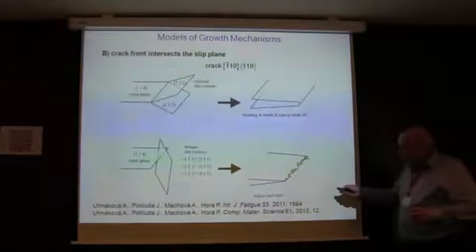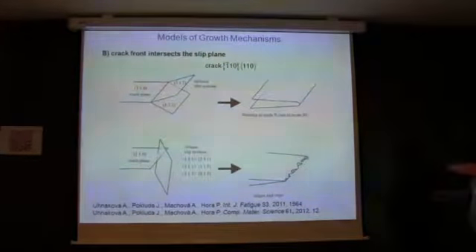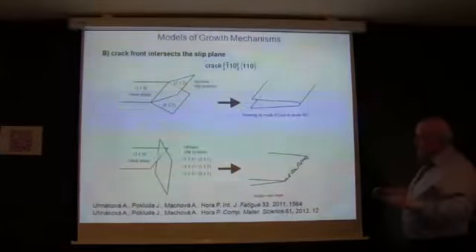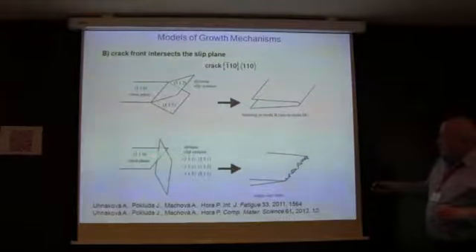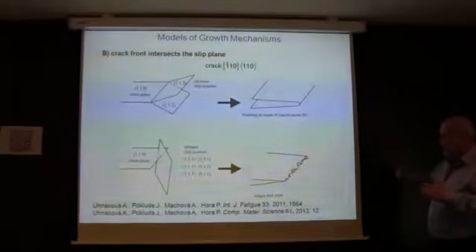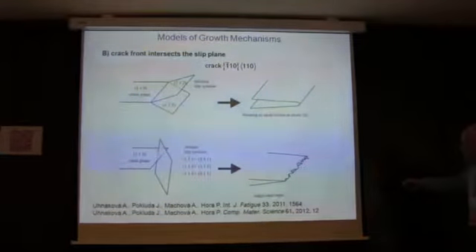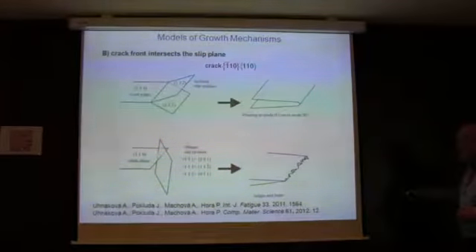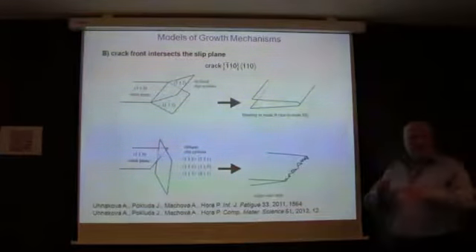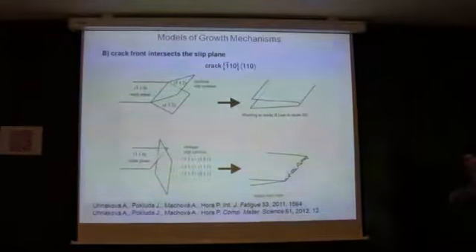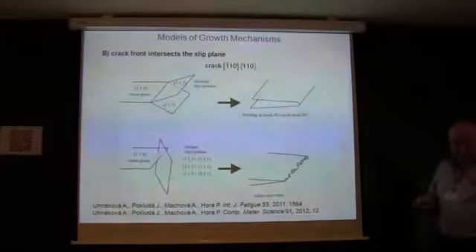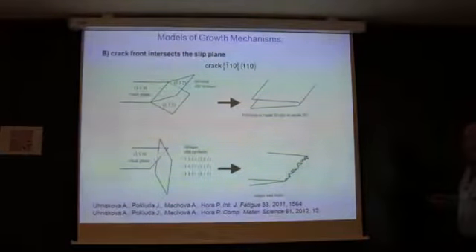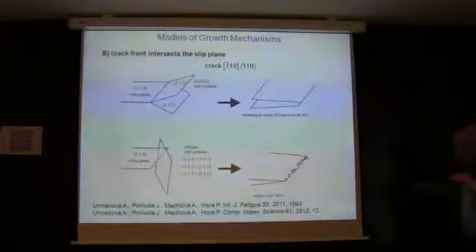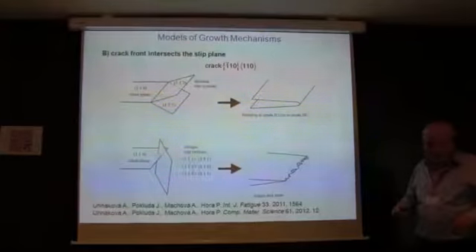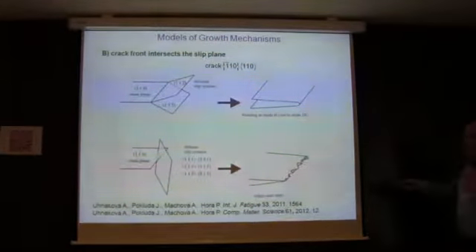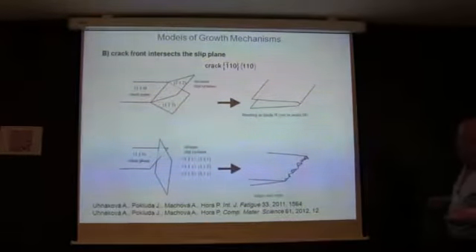But if you have slip systems that are not deflected, but inclined, oblique slip systems like this for example, you can get some dislocations on those oblique systems, interaction of dislocations, and you get some steps at the crack made by this. In a process zone here, you can get interaction of dislocations and creation of vacancies and twins, and other cases, because we modeled it in a molecular dynamics model. So you can create small cracks inside it, and then the crack propagates with the coalescence of the main crack and the small cracks. So in this case, both mode 2 and mode 3 can propagate with a similar mechanism.